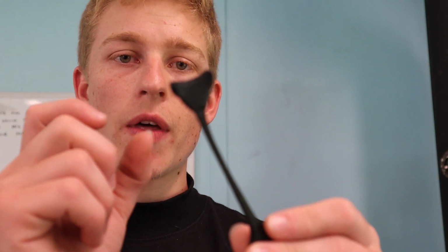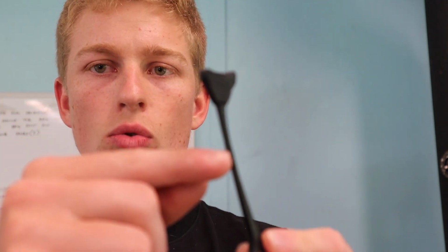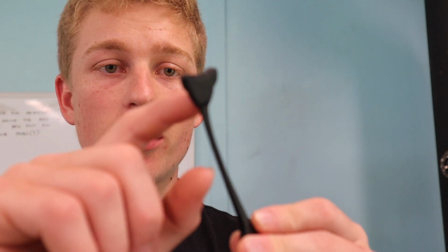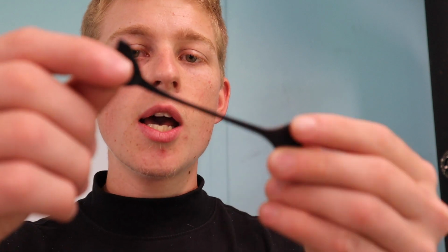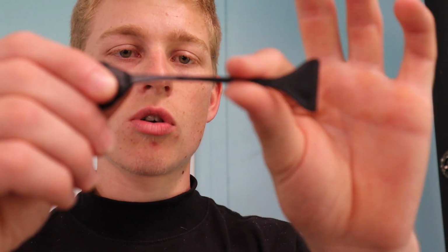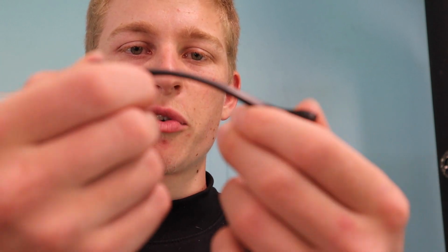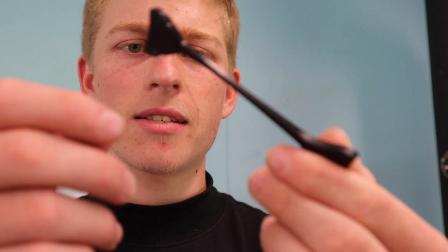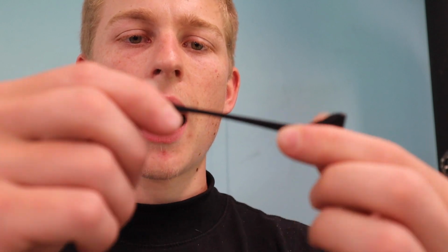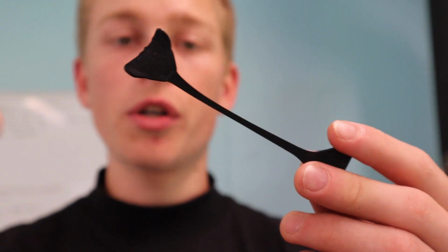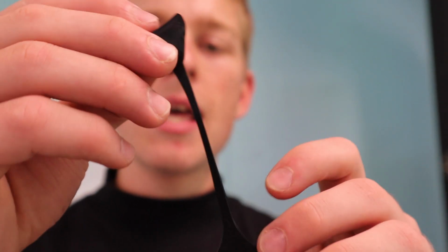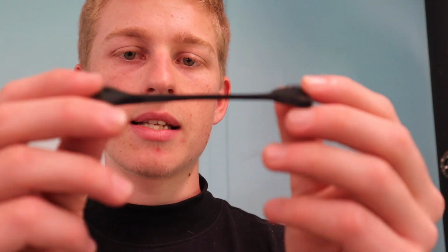So what happened was it's just a focused amount of heat blowing on that sample there that I had the thermocouple a little bit too low, and it was actually like 160 degrees Fahrenheit up here, and that's what actually stretched it. So the problem is getting an even temperature all across the sample with a hot air gun isn't going to be really easy. But as you can see, the temperature resistance of this stuff isn't the best. So that was pretty hot. That's pretty high temperatures. It's hotter than you're going to find in your car, for an example. But this test is going to need more work because obviously that result is not going to be consistent because the sample was not heated evenly.